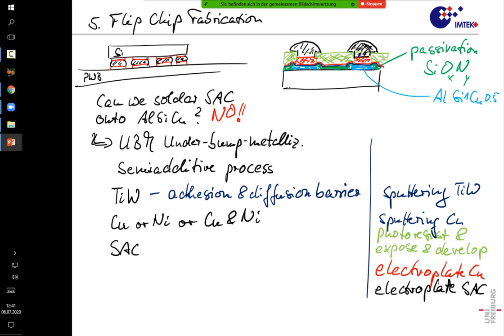Why is electroplating such a good process here? Because it, first of all, selectively attaches onto the copper, and secondly creates those round shapes isotropically, which are similar to bumps. There is one other point which is important. Using Faraday's law, you can determine the thickness or the amount which is deposited very well. And so just by measuring your current in the electroplating, you know precisely how much tin you deposited.